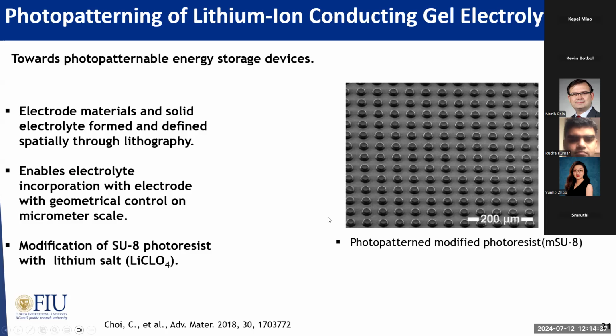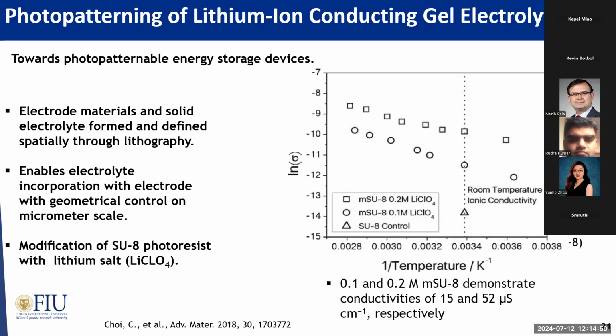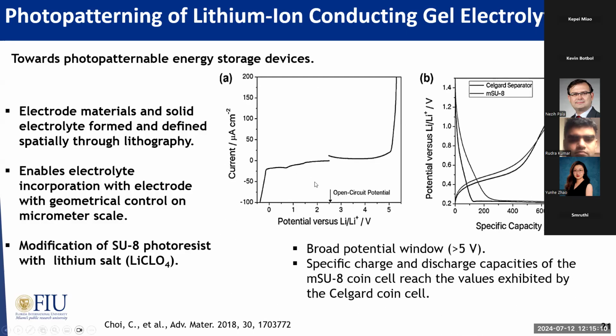So the effort, collaborating with Bruce Dunn after I came back from my first sabbatical, we were developing photoresist-based photopatternable electrolyte. So this is the solid electrolyte. Maybe we can call it a semi-solid electrolyte, but it has a performance almost equivalent to the commercial separator and the commercial solid electrolyte. So we were able to create this modified photoresist electrolyte, which has a very broad potential window. And when we assemble a battery using this modified SU8 electrolyte, we compare it to Celgard separator. It has a very similar performance.